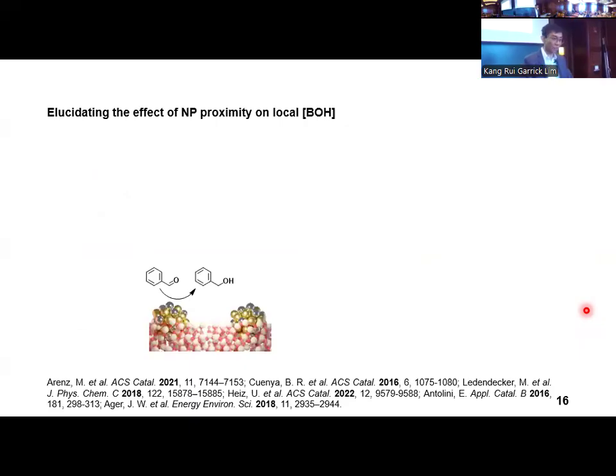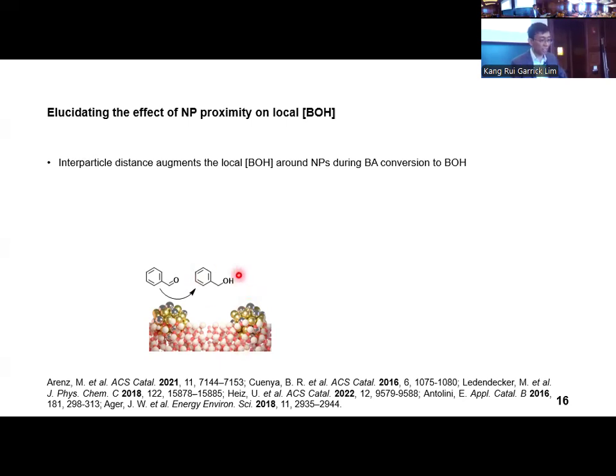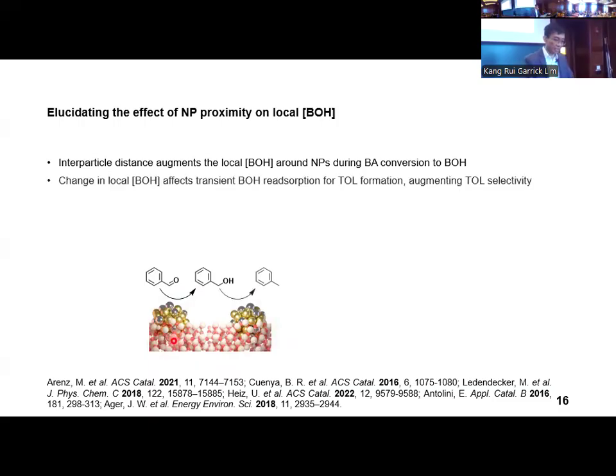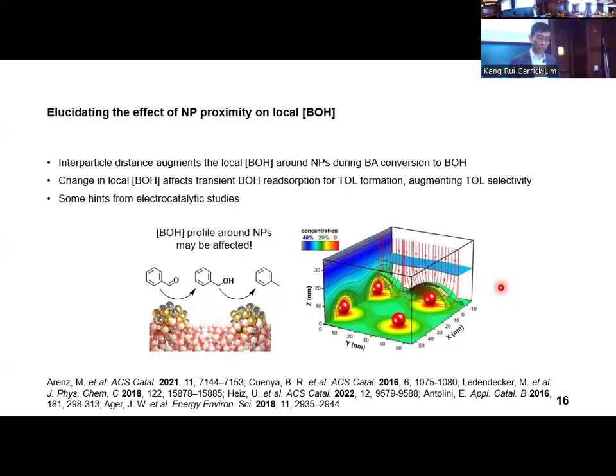We thus investigated how the interparticle distance affects the local benzyl alcohol concentration to explain the high, rapid, and proximity-dependent toluene production during benzaldehyde conversion. Since the nanoparticles actively produce benzyl alcohol during benzaldehyde conversion, we hypothesized that nanoparticle proximity plays a pivotal role in augmenting the benzyl alcohol concentration profile locally around the nanoparticles. This would consequently affect transient benzyl alcohol diffusion and reabsorption onto the nanoparticles for toluene formation. Similar phenomena were proposed in electrocatalysis, but it's not fully clarified in thermocatalysis, possibly due to the high propensity for nanoparticle sintering in conventionally prepared catalysts under typical thermocatalytic reaction conditions.